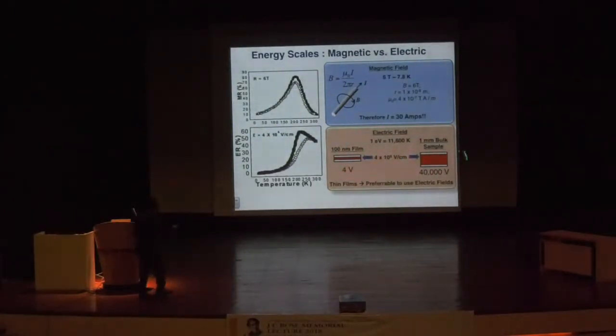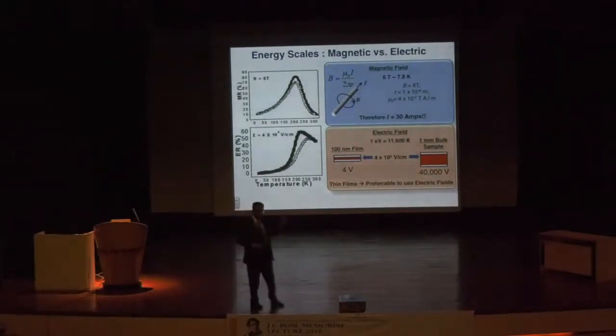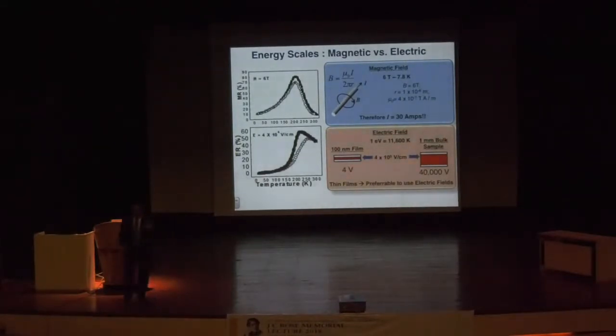At the bottom, I'm giving you the other quantum mechanical quantity, the electric field, which scales with the dimensions of the object. So if I had to get a field of 400 kilovolts per centimeter for a 1 millimeter type object, which is here, I need 40,000 volts, which is shocking, which is a very large voltage. On the other hand, if it's a 100 nanometer thick sample, or even better, a 10 nanometer or 1 nanometer thick sample, that voltage is going to progressively decrease.